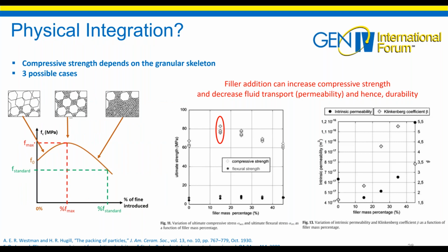The compressive strength depends essentially on the granular skeleton. The addition of fines will fill the voids in the cementitious matrix and increase mechanical performance. There are three different cases. The first case is where the quantity of fines is not sufficient. The second case is with filling of voids. And the third case is with destabilization of the granular skeleton. Thus, only the second case can increase mechanical performance. This allows an increase in compactness.